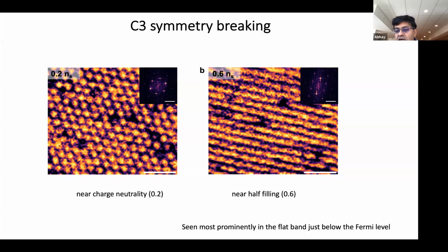And so if you were to characterize the Q of this state, it would be a Q equals 0 state. So you can see that every row of atoms is as bright as every other row of atoms. I see. So we don't see any non-zero Q associated with this, which is why we would call this a nematic. Okay. Thanks. Abhay, in a twisted bilayer case, do you see some sort of variations in the orientations?